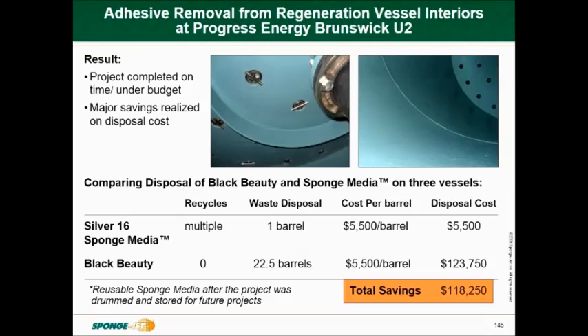This tile does, I apologise about that. The overall saving on this project was significant. That's a whopping 22-to-1 ratio as far as the savings are concerned between doing it with copper slag, and I will put copper slag in the same bracket as garnet. The harder the surface is to remove, the more benefit SpongeJet becomes. Garnet will break down a lot quicker than the media or than the aluminium oxide.